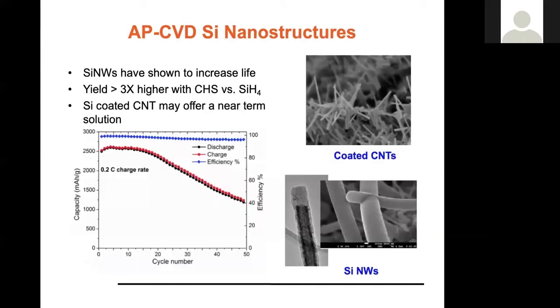So we see here, and I should preface this by saying this is very early work, so no optimization has been done. Bare silicon nanowires have a very high capacity, almost a factor of 8 higher than graphite at a modest charge and discharge rate of 0.2 C. We see good cycle life over the first 20 cycles, and then a decrease in the overall capacity. More work needs to be done here, but the thing I'd like to point out is that the coulombic efficiency of this process remains high.